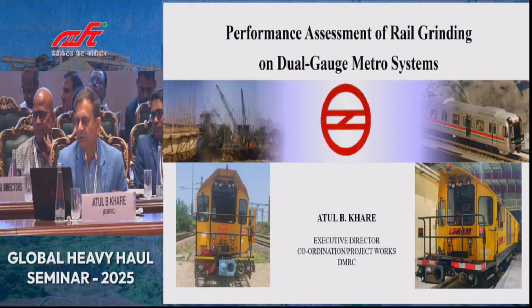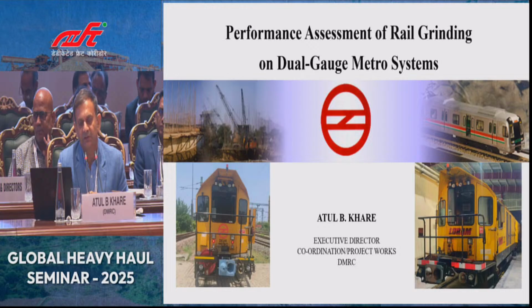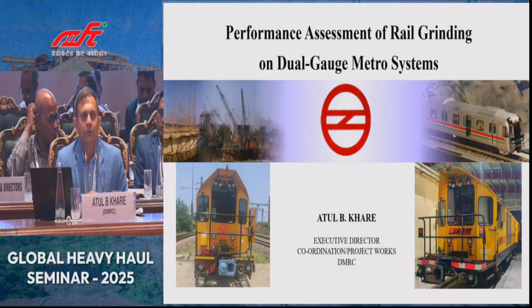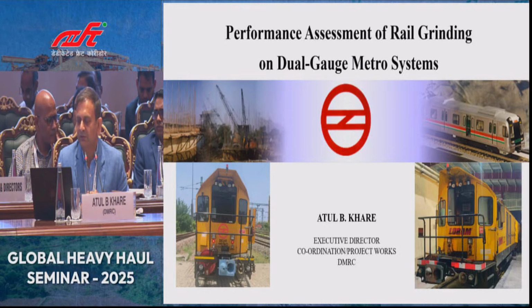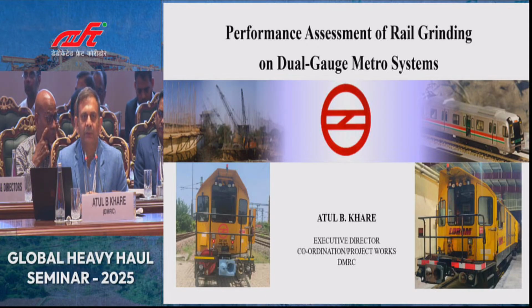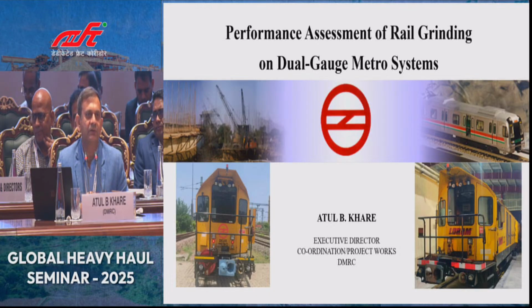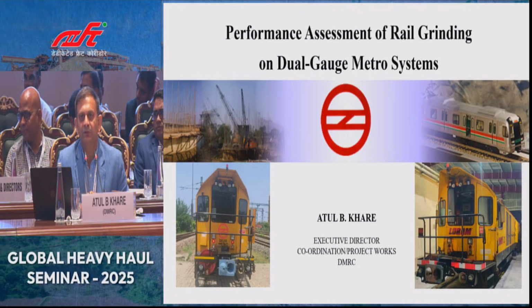Many authorities have adopted standard gauge worldwide, but DMRC, due to legacy, is operating on broad gauge as well as standard gauge. So the issue being faced as of now is the accelerated rail degradation, generation of surface defects, which is induced by, of course, continuous rail-wheel interaction, and at times unfavorable rail-wheel interaction, which is generating surface defects, may lead to groundborne vibration, especially at the locations where we have not carried out any vibration mitigation measures due to legacy.